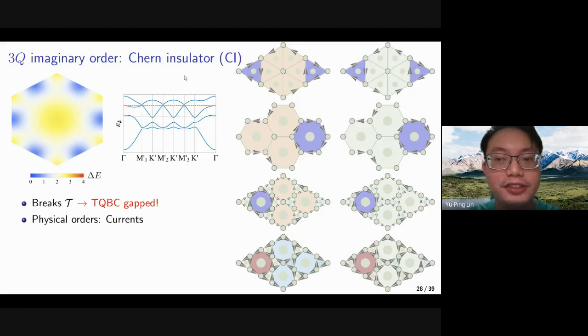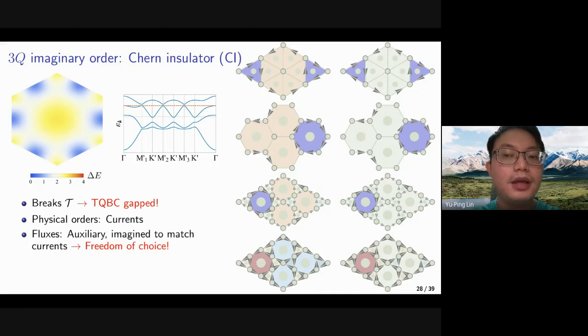Meanwhile, we should notice that the physical orders for the imaginary orders are the current orders, because they are the expectation values that we're really evaluating. But we can imagine some kind of flux orders which penetrate the triangles or the hexagons. And these fluxes are auxiliary, which are imagined to match the physical currents on the bonds. So we have a degree of freedom to choose the flux order.